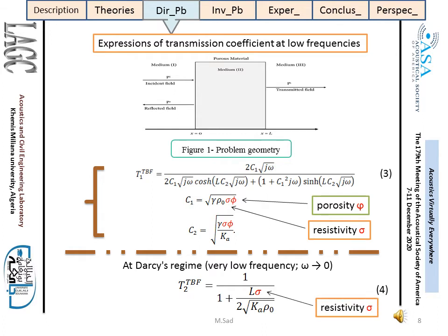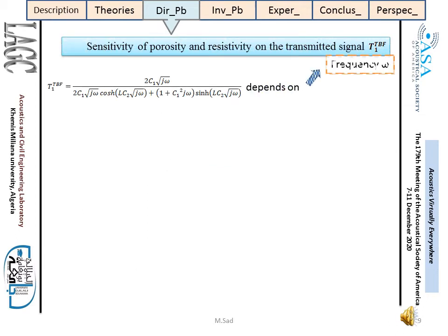At that regime, very low frequency, and by taking into account only the first term of the Taylor series development, expression T2 of the transmission coefficient is much simpler. It's given by equation 4. This expression T2 is independent of frequency and porosity and depends only on the flow resistivity sigma. The transmission coefficient T1 depends on the frequency, the porosity, and the flow resistivity.